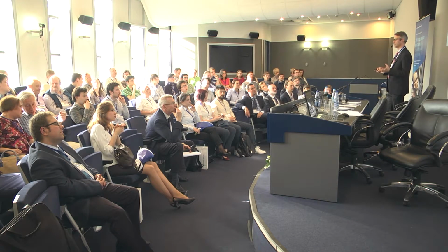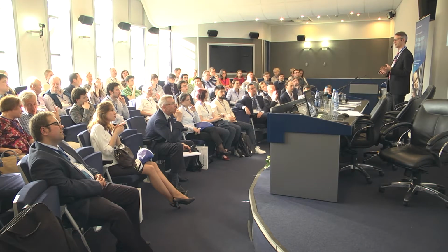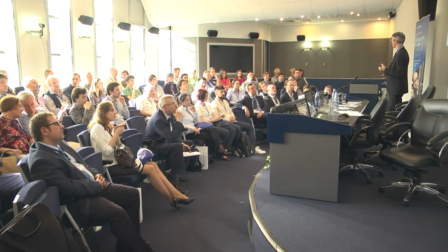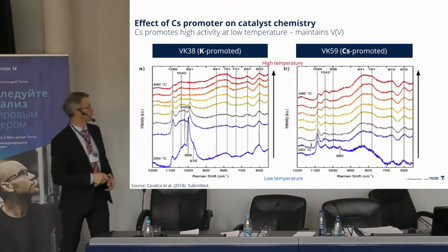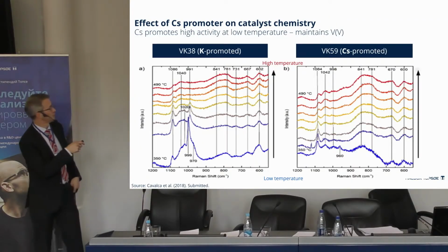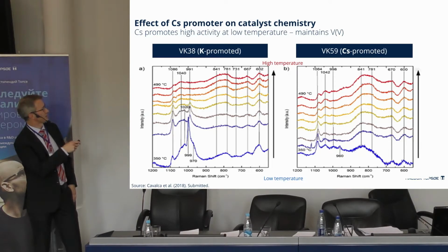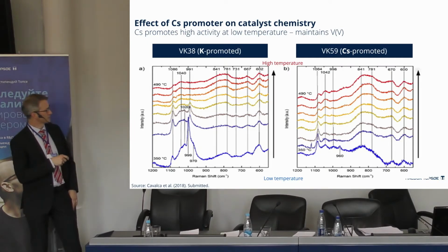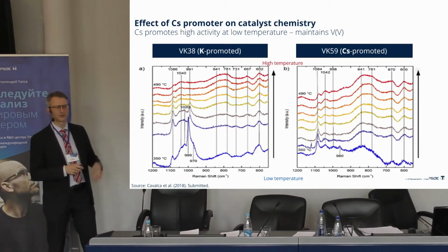Another study we did was to investigate what the effect of cesium as a promoter is. The standard catalyst uses primarily potassium as the promoter, and we wanted to see what cesium does, because cesium is used to boost activity at low temperature. Here we've done a similar experiment. We have two commercial catalysts. One is potassium promoted, one is cesium promoted, and we do the Raman spectra from 350 degrees up to 490, so this is increasing temperature.